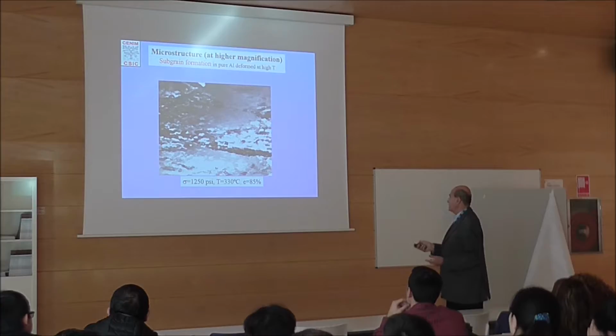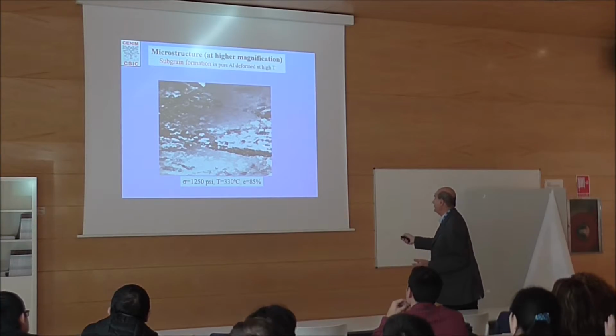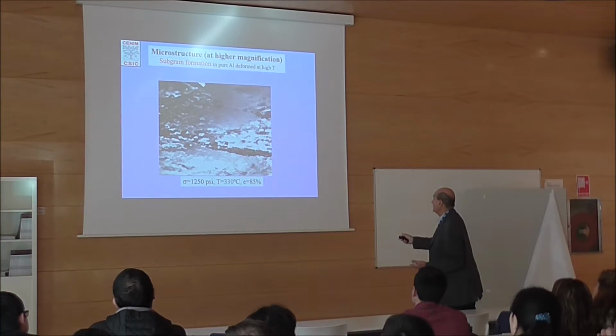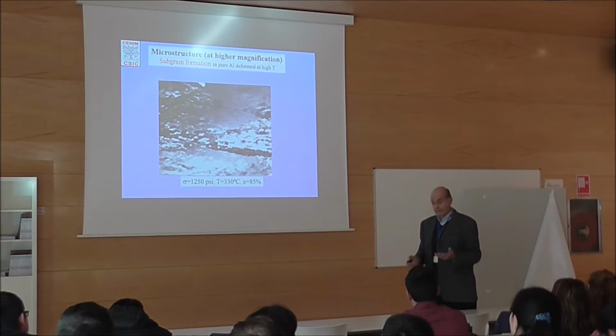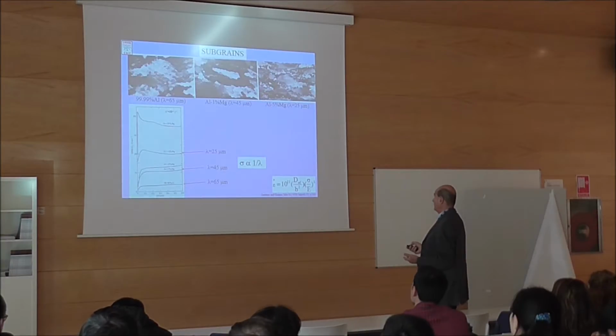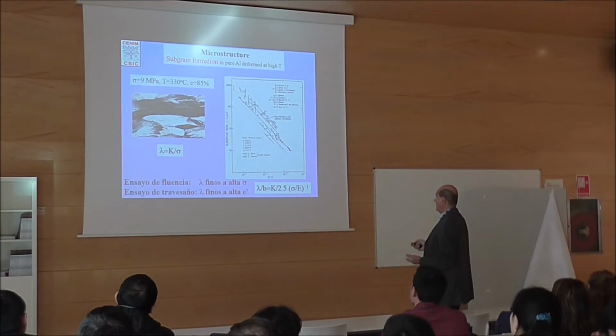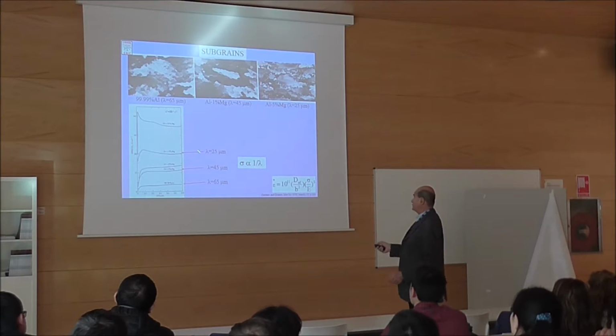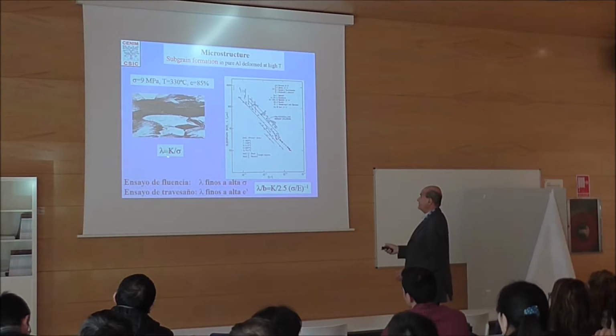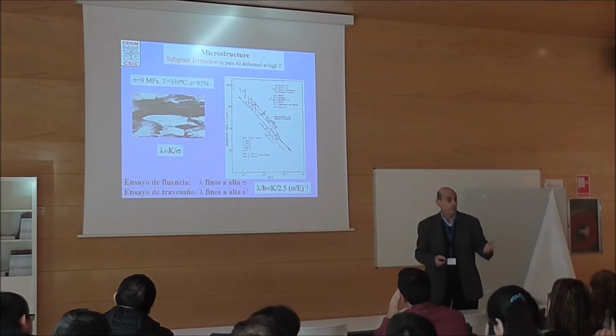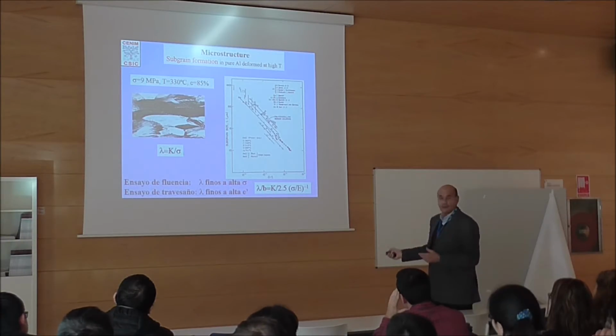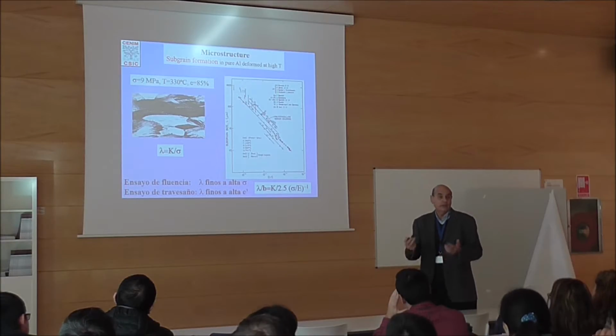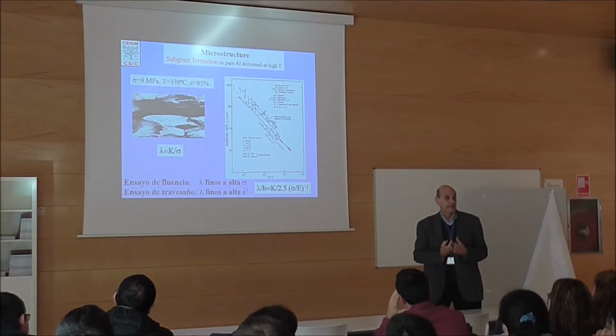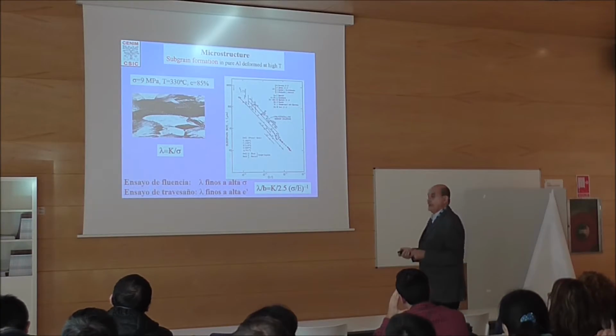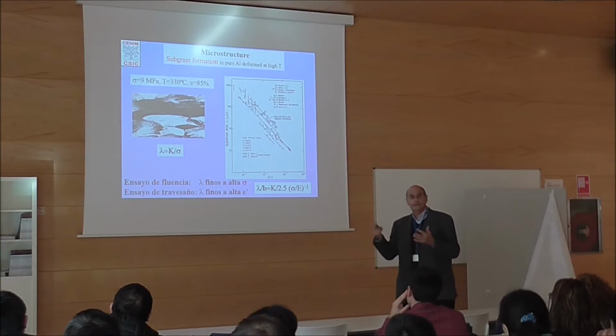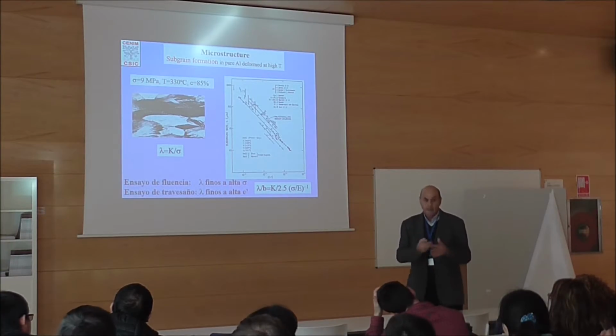And this is a high magnification picture. You have the grains, you see a very big grain, and here the subgrains, probably 4 or 5. And the correlation is this. The subgrain size, and this is a very fundamental and very important thing, is inversely proportional to the stress. The higher the stress, the lower the subgrain size. This is very fundamental and very important. It will not depend on deformation. People think, wow, we have a lot of deformation, so the subgrains will be smaller. No, it will depend on stress.